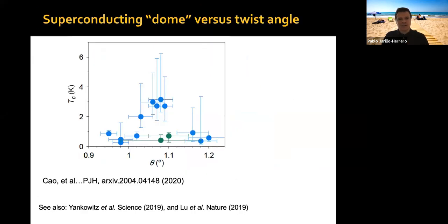Now, one of the things that I mentioned is that the properties are very dependent on twist angle, okay? So for example, this is just an example from over a dozen of our superconducting devices, and what is the TC versus twist angle, okay? Usually you hear superconducting domes in cuprates and other materials, you have TC versus some parameter like doping or sometimes pressure. Here we can do something which is really unique to 2D materials, which is plot a TC at optimal doping versus twist angle between these two crystalline lattices, okay? And what you can see is that there is a range of twist angles over which we can see superconductivity, okay?